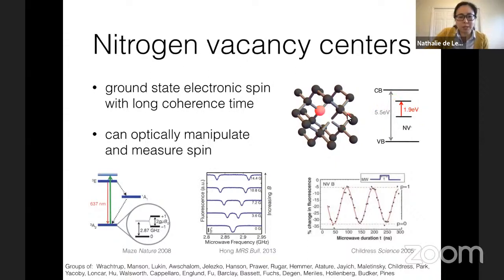The NV center in particular is an electronic spin 1 defect that has extremely long coherence times even at room temperature. You have a spin lattice relaxation time of around 10 milliseconds, and your T2 is generally limited by what kind of nuclear spin bath you have. And it turns out that there's a really convenient way to optically manipulate and measure the spin. Even at room temperature, there's a scheme for doing off-resonant excitation and spin readout.